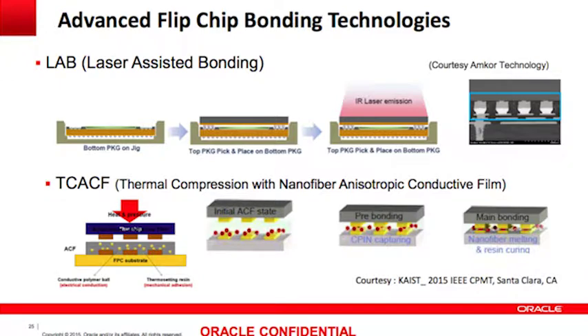A couple of examples of other process technologies is this laser-assisted bonding. So copper bump requires some compression bonding, like mechanical pressure. But that requirement limits die size or bump count, like about 4,000 or 5,000 bumps. But eventually, what I have today is 20,000, almost 21,000 bumps within one chip. So I cannot use thermal compression. But this laser supports it, eliminating that mechanical pressure. Just a couple of seconds of IR laser emission makes it happen.